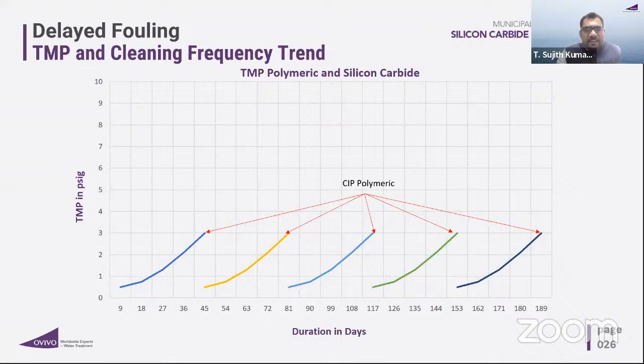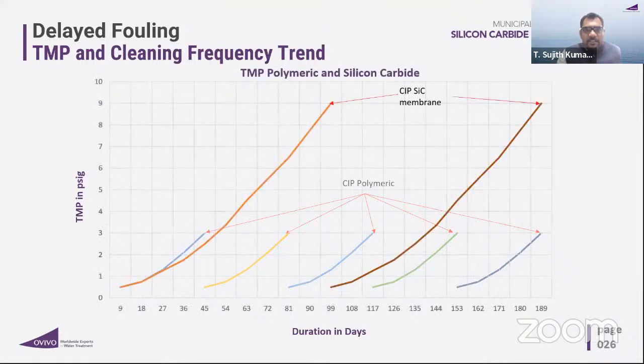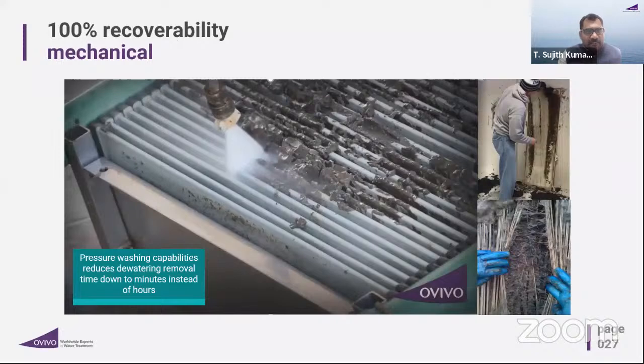polymeric membrane needs cleaning every 45 days. If you go with any silicon carbide membranes, the cleaning would be around 90 days. That is 3 months. That means you are delaying the cleaning. When you delay the cleaning, you are saving on chemical, you are saving on flux, everything.